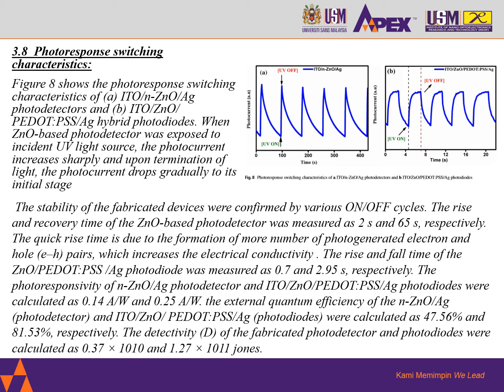The quick rise time is due to the formation of a larger number of photo-generated electron and hole pairs, which increases the electrical conductivity. The rise and fall time of the zinc oxide/PEDOT:PSS/silver photodiode was measured as 0.7 and 2.95 seconds respectively. The photoresponsivity of the ITO/zinc oxide/silver photodetector and ITO/zinc oxide/PEDOT:PSS/silver photodiodes were calculated as 0.14 and 0.25. The external quantum efficiency was calculated as 47.56% and 81.53% respectively. The detectivity D of the fabricated photodetector and photodiodes were calculated as 0.37×10¹⁰ and 1.27×10¹¹ Jones.